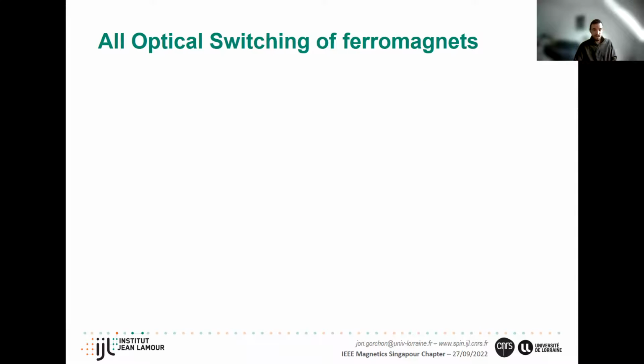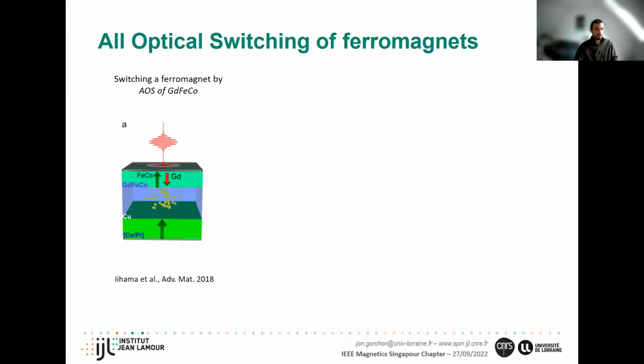So the avenue we've been going down for a few years now in the group is that we're trying to grow synthetic layers and try to induce switching in remote layers via spin currents. So we started with this gadolinium iron cobalt layer, which we could switch optically. And then we use a copper spacer every time and put some ferromagnetic layer far away from the gadolinium iron cobalt. And so when we shoot a femtosecond laser at these kinds of structures, what we observe is that we can not only switch the gadolinium iron cobalt layer, but we can also switch the cobalt platinum layer.